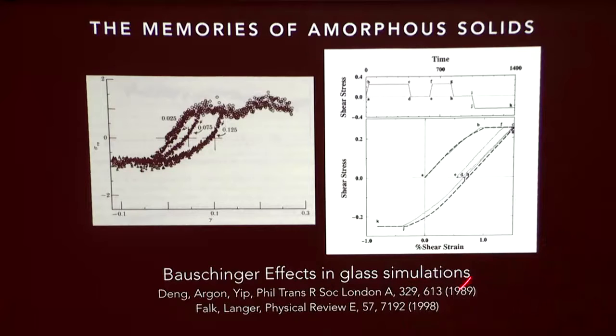We had seen this back when I was doing my grad work, where we would load a glassy system using molecular dynamics simulation, unload it, reload it. It would behave more or less elastically on reloading, but if you loaded it in the opposite direction, it was softer. So somewhere in the microstructure of the material, there's something encoding the fact that I've been loaded in this particular direction before - and that if you load me in that direction again, I'm going to be hardened up to a high stress, but if you load me in the opposite direction, that's not going to be the case.